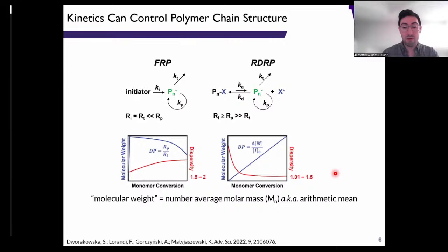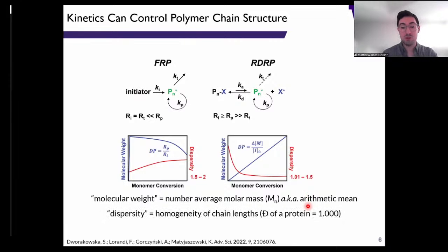So just to reference some of these terms and break them down into more tangible bites, molecular weight for our purposes is just going to be the number average molar mass, aka the arithmetic mean. So we're going to make a lot of different sizes of polymer chains, and we're going to sum up the number of repeat units in each particular chain and divide by the number of chains to get some particular arithmetic mean. This term dispersity in red gives me a measure of the homogeneity of chain length.